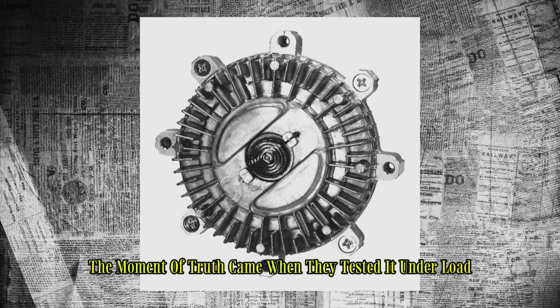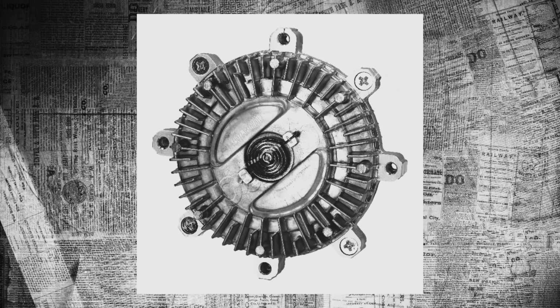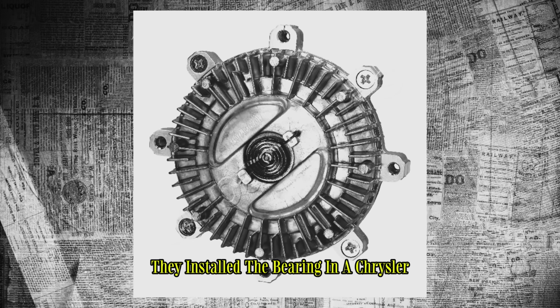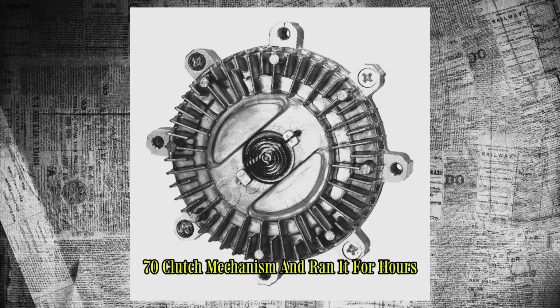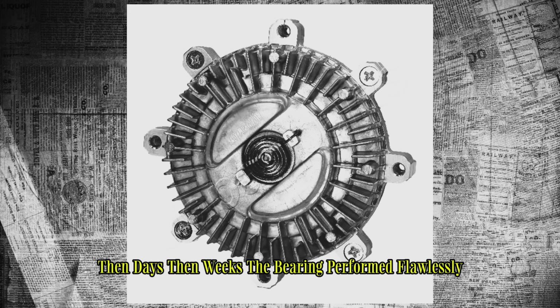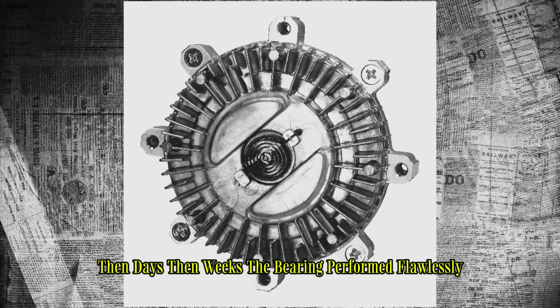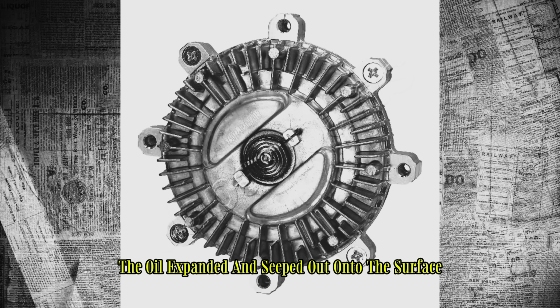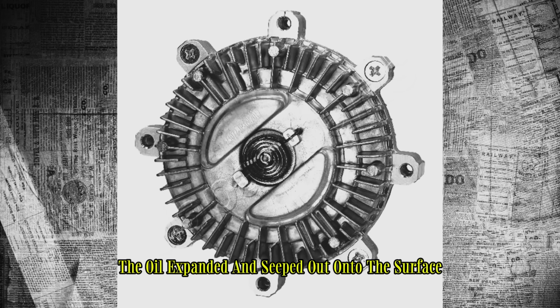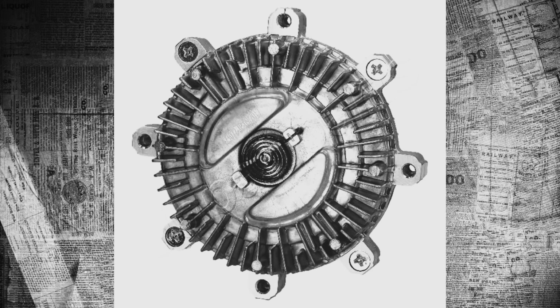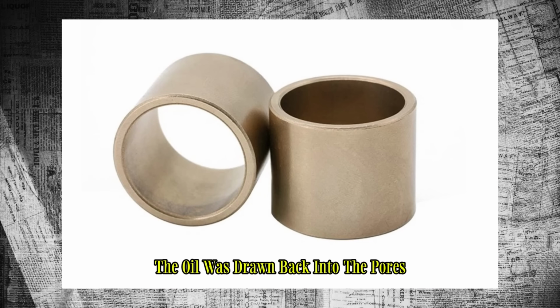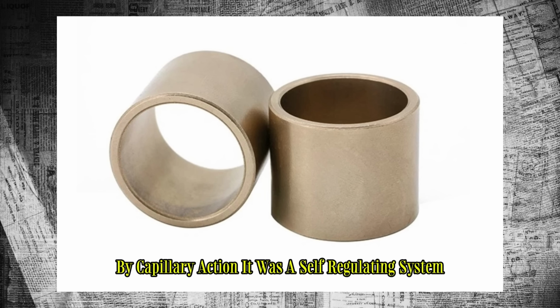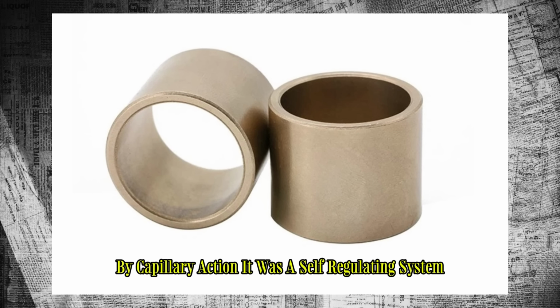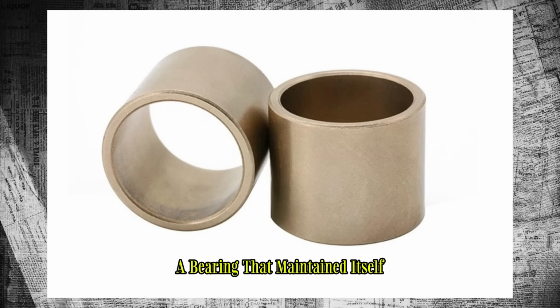The moment of truth came when they tested it under load. They installed the bearing in a Chrysler fan clutch mechanism and ran it for hours, then days, then weeks. The bearing performed flawlessly. When friction heated the metal, the oil expanded and seeped out onto the surface, lubricating the contact point. When the bearing cooled, the oil was drawn back into the pores by capillary action. It was a self-regulating system, a bearing that maintained itself.